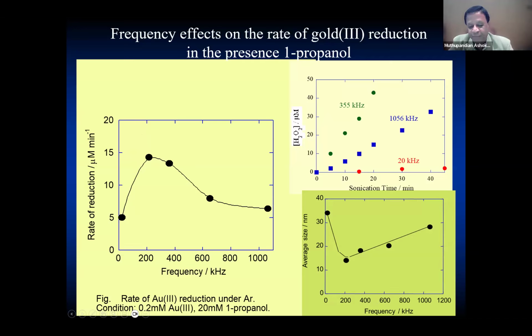Again, those who are working in the materials area know that when you try to form particles, there are two competing processes, nucleation and growth. If you can increase the nucleation rate, the particles will be smaller. If you increase the growth rate compared to the nucleation rate, the particles will be much larger. So when I produce a large amount of radicals, the nucleation rate of the gold particles is higher. The higher the nucleation rate, the smaller the particles. So basically what I'm trying to show here is that by controlling the frequency, I can control the size of the metal nanoparticles that we generate.